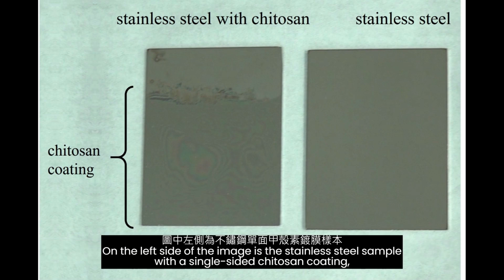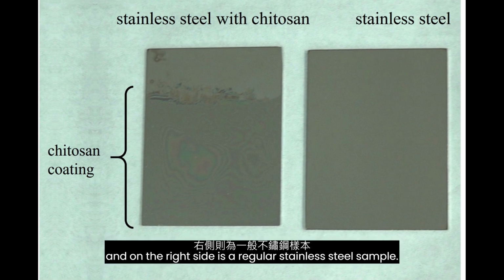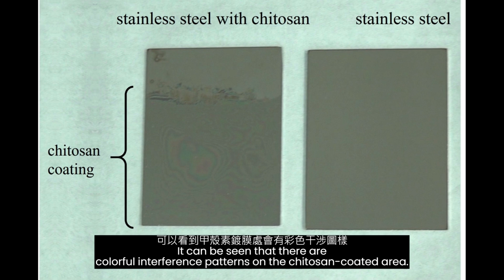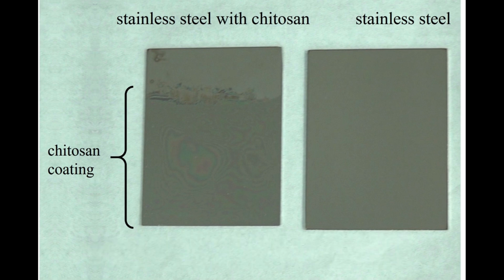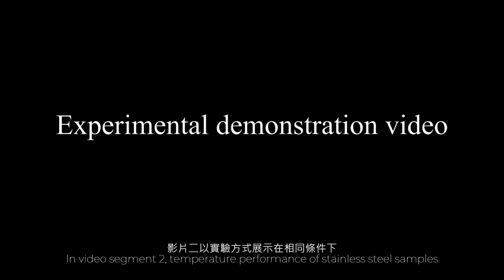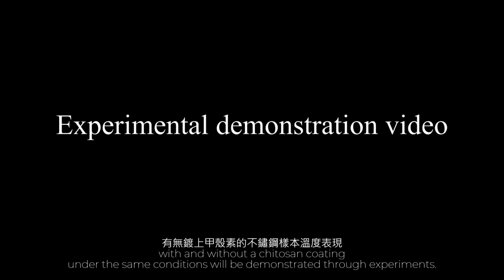On the left side of the image is the stainless steel sample with a single-sided chitosan coating, and on the right side is a regular stainless steel sample. It can be seen that there are colorful interference patterns on the chitosan-coated area. In video segment 2, temperature performance of stainless steel samples with and without a chitosan coating under the same conditions will be demonstrated through experiments.